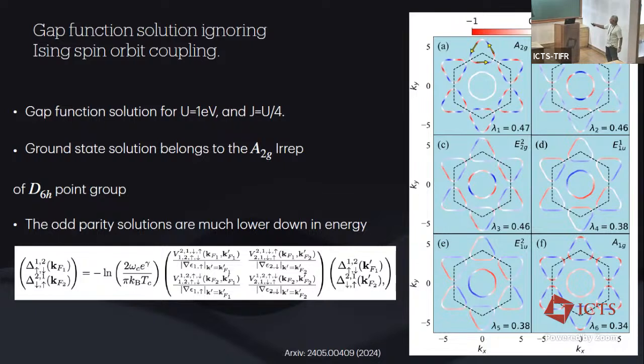So the ground state solution is given by this, and you can see that for the ground state solution, indeed you find that for the gamma-centered pocket, the gap magnitude is much smaller than what you have for the k-centered pockets. This was along the line that for a slightly different mechanism, Igor Mazin and Dan Agterberg's paper, they were arguing for the presence of the collective modes. But the ground state here belongs not to the A1g or the s-wave representation, but to the A2g irreducible representation of the D6h point group.